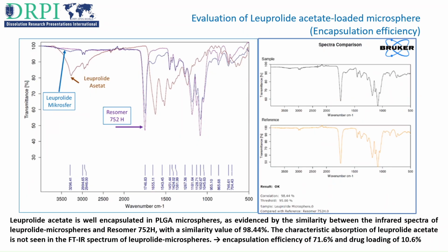The FTIR characterization showed successful encapsulation of Leuprolide acetate in PLGA microspheres, as the characteristic peaks of Leuprolide acetate were no longer visible in the microsphere spectrum. The infrared spectra of the final microspheres showed high similarity to pure PLGA, around 98.44%, and the actual drug loading was 10.6% with encapsulation efficiency of 71.6%.